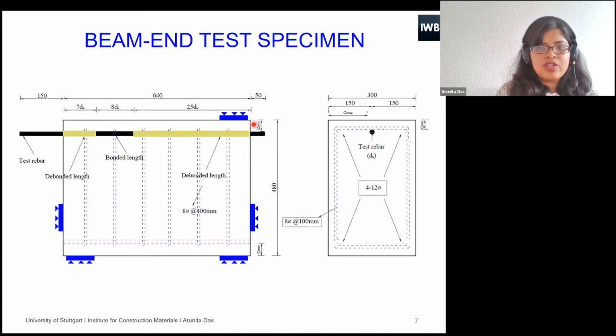And the restraints which are provided during the pull-out test: the whole procedure was that the specimens were first cast, and then placed in the furnace for a certain time of fire. Then they were allowed to cool down naturally. Then they were taken out from the furnace and they were pulled out.